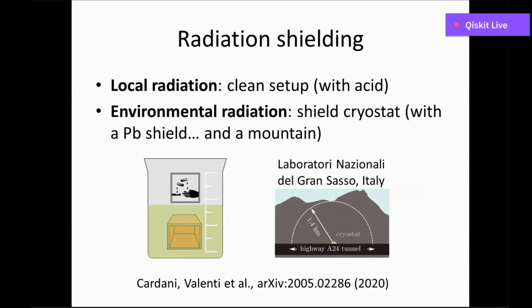Yeah, but indeed, our phonon coupling efficiency is very small actually. It's some fraction of a percent. That's something that I think was in one of the questions before, how we were so sensitive to phonons, and actually I wouldn't say we are so sensitive to phonons. People that do this kind of devices for MKIDs or other kinds of particle detectors have an efficiency which is at least two orders of magnitude higher compared to the efficiency for phonon absorption that we have with these kinetic inductance detectors.